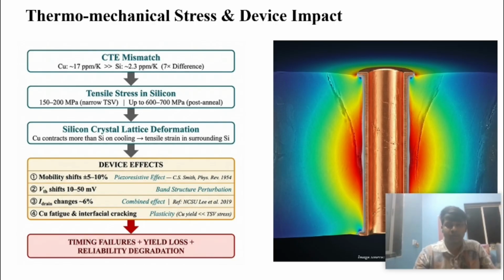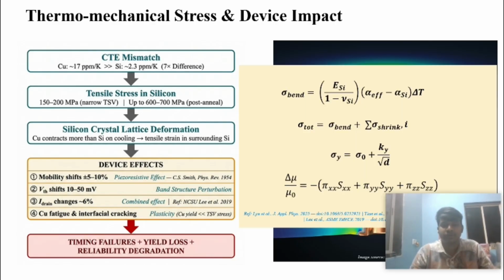So we can see some formulas for that. The first two formulas talk about total stresses. There is a superposition of bending stresses due to warping of the silicon wafer and also shrinkage of copper. The third equation is the change in yield stress due to the grain size effect, and the decrease in grain size. So that talks about the microstructural point of view.